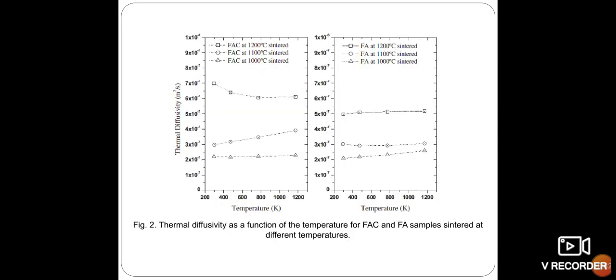The next one is the representation of the temperature versus thermal diffusivity for the FAC and FA samples sintered at different temperatures. So the square represents the samples sintered at 1200 degrees centigrade, the round represents 1100 degrees centigrade, and the triangle represents 1000 degrees centigrade.